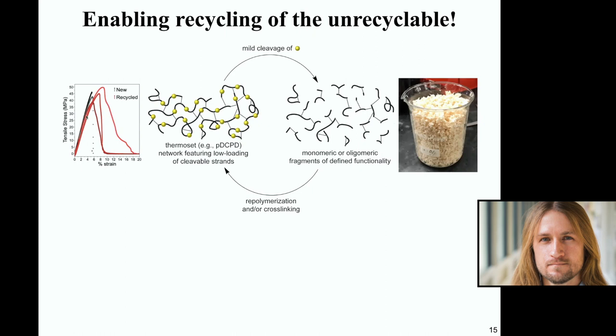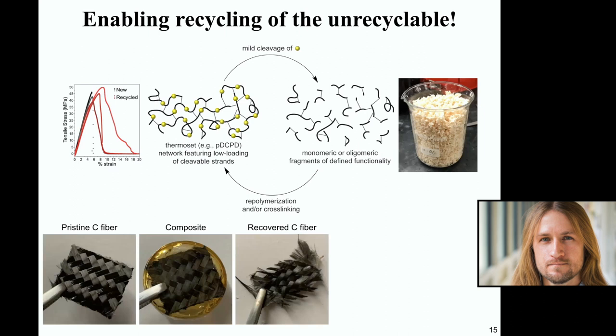So these two curves are what we call stress-strain curves, where we're measuring essentially the stress, which is the force we apply to the sample, and how much it stretches, how much it strains. And you can see that these two curves overlap. However, the recycled samples actually can be stretched even further and have a higher area under this curve, which means enhanced toughness. So we're very excited about this as a strategy to not only recycle, but potentially make new materials with some improved properties.